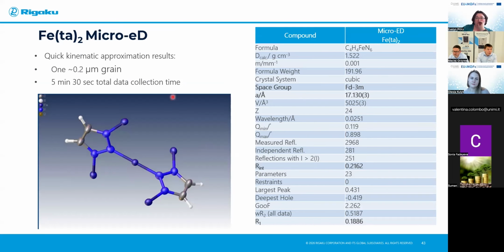So this is an example of this triazolate iron MOF. And I was able to solve it from just one grain of a size of basically micrometers. The whole data collection was 5 minutes and 30 seconds. And basically, the whole analysis is like 1 hour or something like that. And it was in very good agreement with the solution that Maciej obtained from the powder data, but it allows us to understand all the basic changes that are happening during the phase transition.